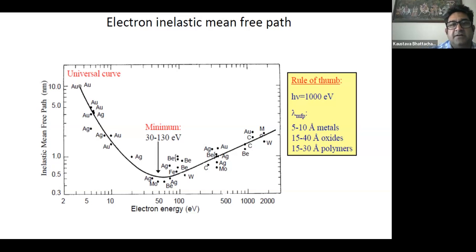It should be within its mean free path. If it is not within its mean free path, then it will be colliding with different materials, and then the kinetic energy that we will be measuring will be erroneous. So the fewer the molecules, the better. Now if we check the mean free path for all the moieties, beryllium has the maximum. Still, there we require a vacuum of 10 to the minus 7 torr, not 10 to the minus 11 torr.